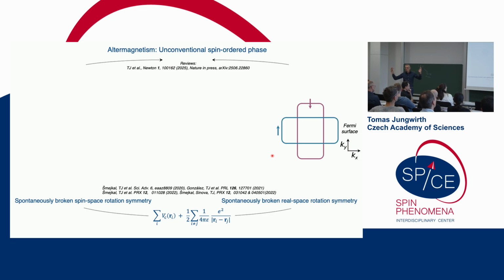And what you see is that the deformation axes are actually different. And because of this, we not only break the real space rotation symmetry, like in the nematic phase, but we also break the spin space rotation symmetry because we have spin polarized Fermi surfaces.